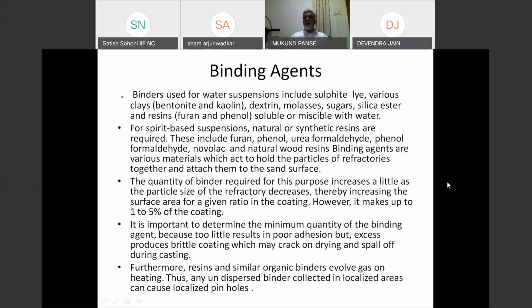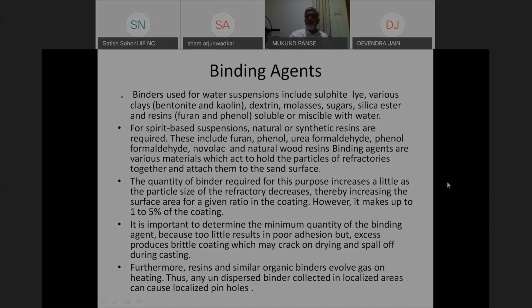It is important to determine the minimum quantity of the agent required. See, if it is high, the coat will crack. If it is low, it will get washed away. So, for the mold sand system you are using, you have to settle on a proper mold coating which gets a uniform coating. You may have to carry out certain trials with different paints, but settle with a paint which gives you an exact uniform coat all over the mold. Furthermore, the binders themselves, when heated, should not evolve much gas because they are resin based.